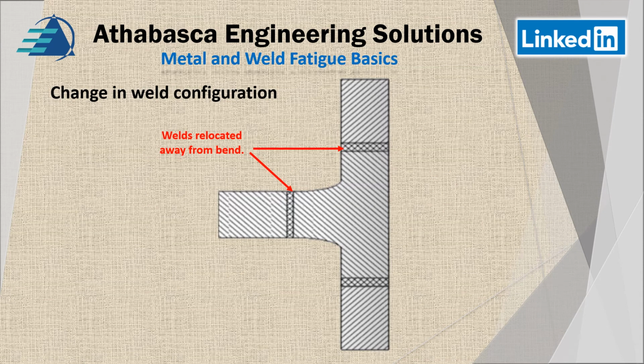Here's an interesting configuration that I used before. This is a strategy that's used sometimes where there's a lot of fatigue, like a coke drum, where there's a lot of cycling going on. We have an area where there's a ton of fatigue, thermal cycling, pressurizing several times a day. This is a very common strategy. Instead of having the weld in the high stress area, you move it off there and put large radiuses on your bends, making sure your vertical loads are directly over, say, your skirt, so the vertical loads translate to the skirt. So that's one very common strategy that's recommended by ASME.